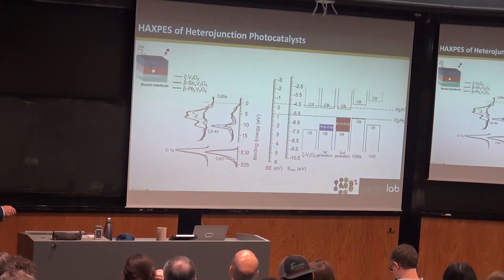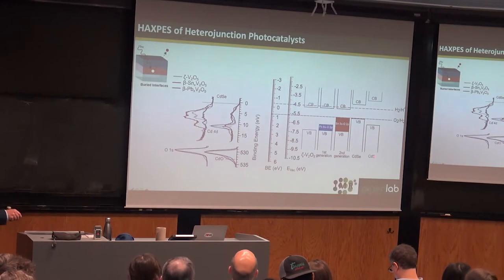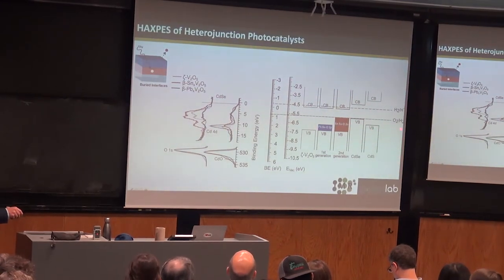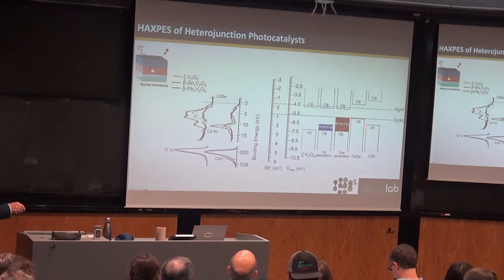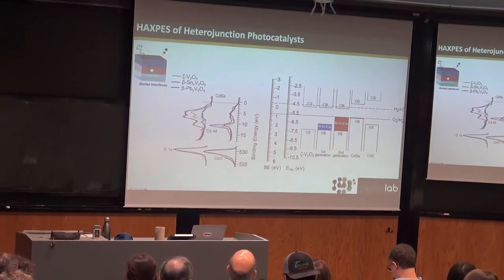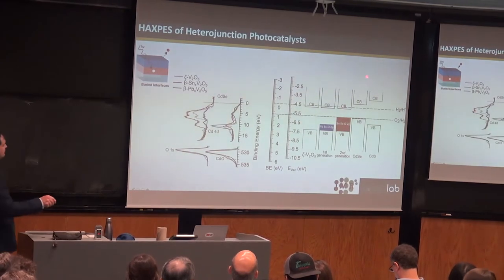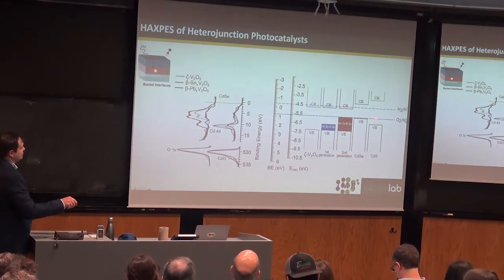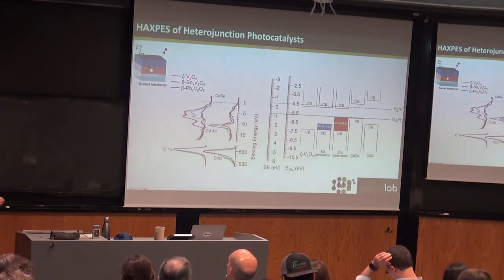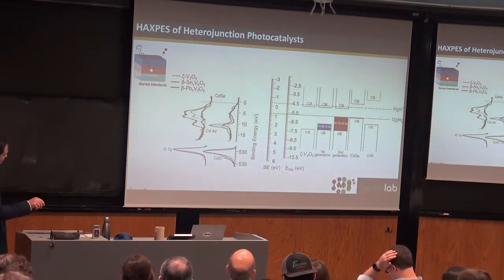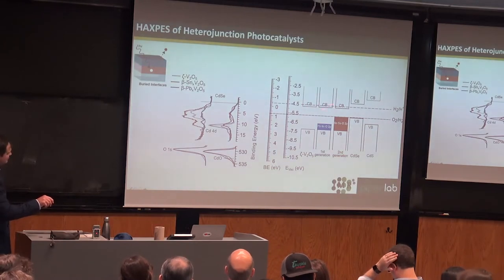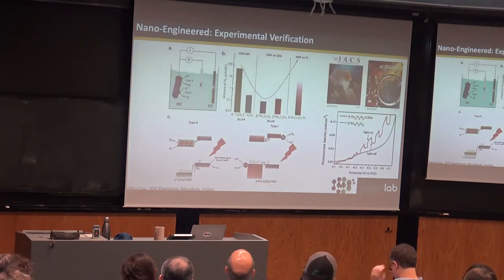So the idea is we take the dopants and we see how we're increasing the formation of those lone pair states and how they align. In the case of lead V2O5, we get really nice band alignment with cadmium selenide. But cadmium selenide has a larger band gap, and we want something smaller so it'd be more efficient with the solar spectrum. So moving to cadmium selenide, we found that the tin V2O5 gave nice alignment. The other thing is by doping it with the tin and changing the polymorph, we remove that split-off band and we partially fill these states because of the reduction. And that becomes quite important when we discuss how this can engineer photochemistry.